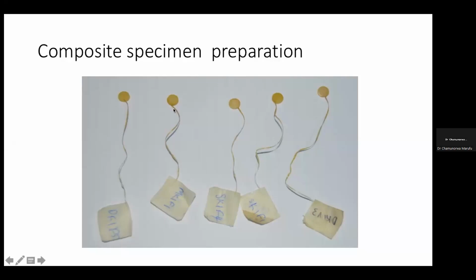So we used a mold to prepare these discs, and we tried to standardize the protocol in which they were prepared, that is in terms of the curing times and the curing light. We actually prepared a jig to mount the curing light so that we minimize the number of confounders. And this specimen had a piece of floss attached to it, and we used it to tie the tag to identify each specimen, and we also used the floss to suspend the specimen